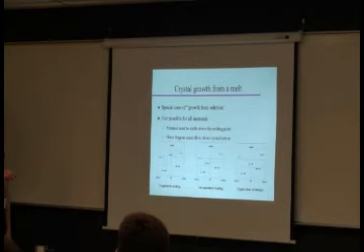If our material melts incongruently, as in this example, we cannot grow from the melt. Because if we had a liquid with a 1-to-1 composition, we cool down, so this y-axis is temperature in this case, we would hit the liquidus curve here. There is no line here. So we have to follow a line. Well, if we keep cooling, we follow this line. So what we'll do is we change the composition of the liquid and we deposit B. We will not be depositing AB directly. We can probably make some nice crystals of B that way, but that's no good if we want to grow AB.